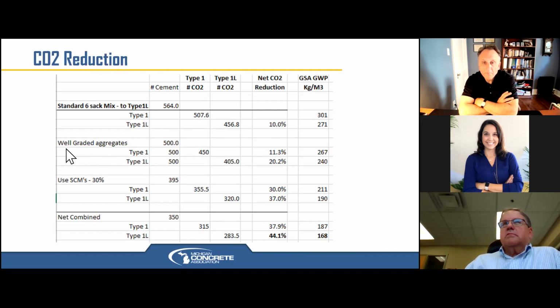In Michigan, since the early 2000s, we've been working with well-graded aggregates, taking out some of the cement paste, reducing the total cement content. That alone, if we just stayed with type 1, is reducing our carbon footprint by 11%. With the type 1L, it's dropping it by 20%.